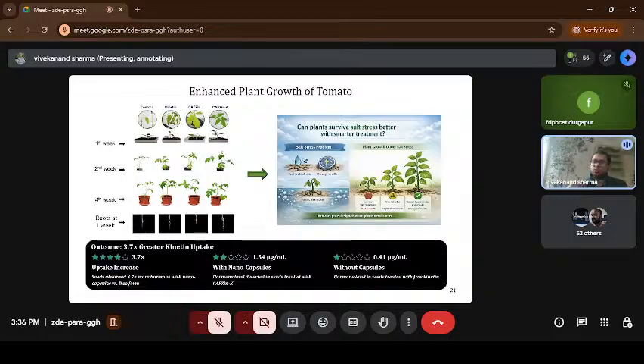So basically we answered the question: can a plant survive salt stress better with a smarter treatment or not? And we found the fundamental result, which I have shown at the bottom: the kinetin uptake by the tomato plant increased 3.7 times compared to without treatment. With the nanocapsule, with our formulation, the kinetin goes into the plant at 1.54 microgram per ml, but without treatment, the kinetin uptake for the tomato plant was only 0.41 microgram per ml. So when we divide 1.54 by 0.41, we get 3.7.